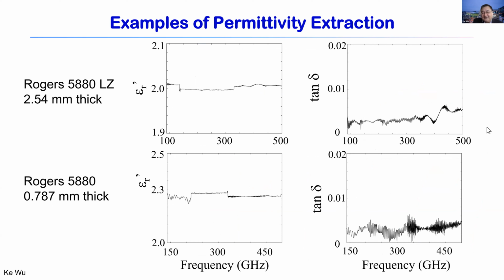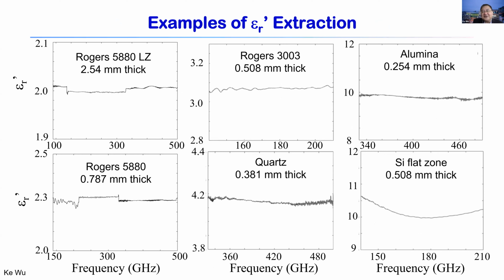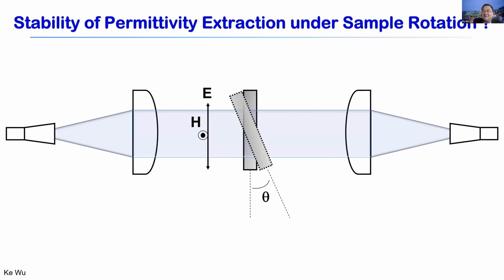And the real part value is pretty good. One of the interesting things about this particular technique is that for thin and thick substrates, the values are quite consistent. But of course, we cannot see whether the loss tangent value is really good or not, because right now the scaling is quite large here. This is the real part value based on these lens-based measurements.